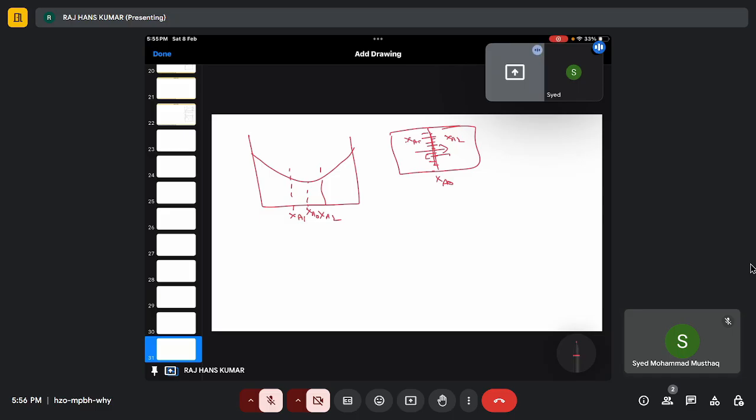Right? Now what happens if I'm having immiscibility, like this? So if I have compositions like here, right, then what happens? If I'm trying to mix these two phases, they will try to come down to this point. Here we have a common tangent. This is my composition. Now, what happened? It is a downhill diffusion because